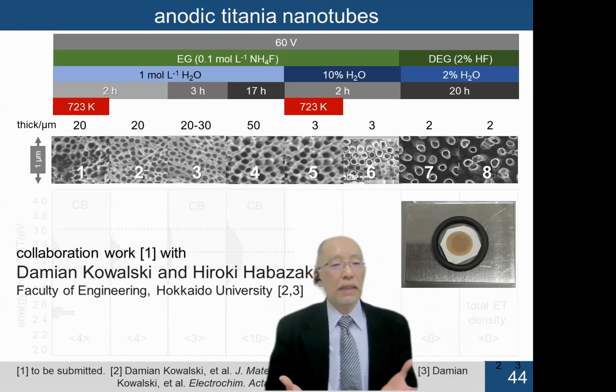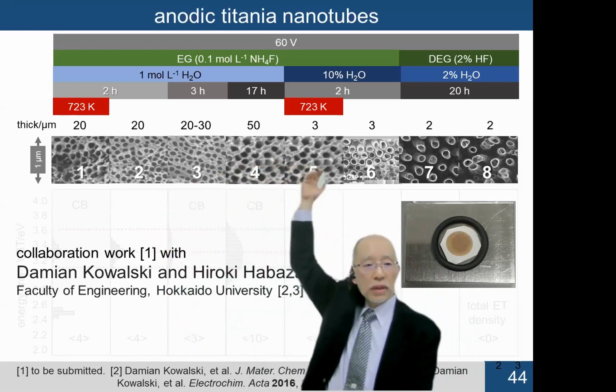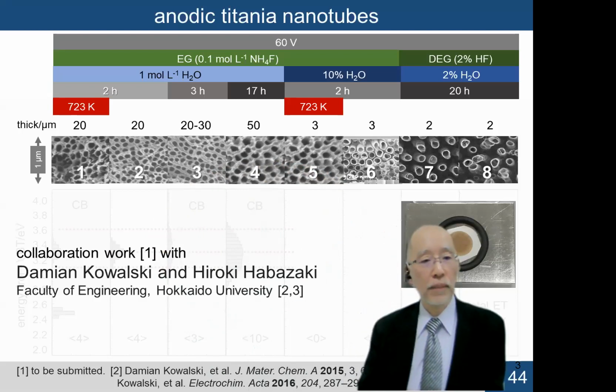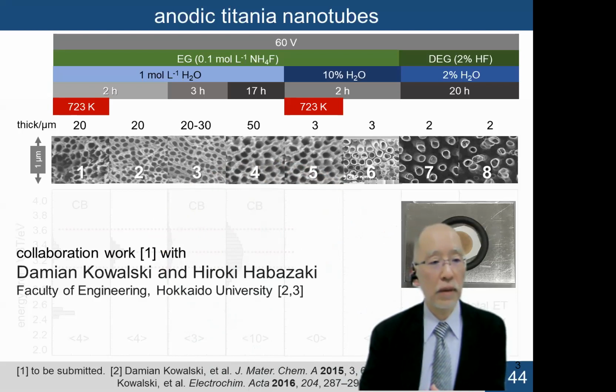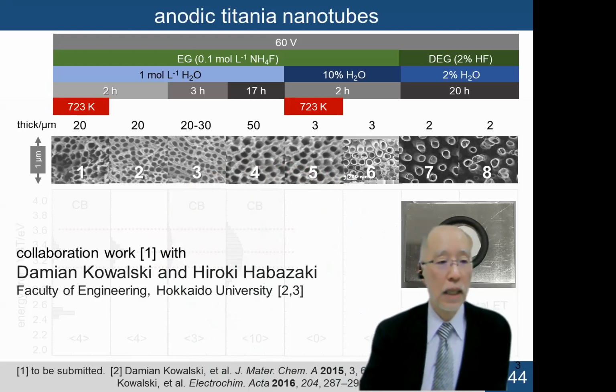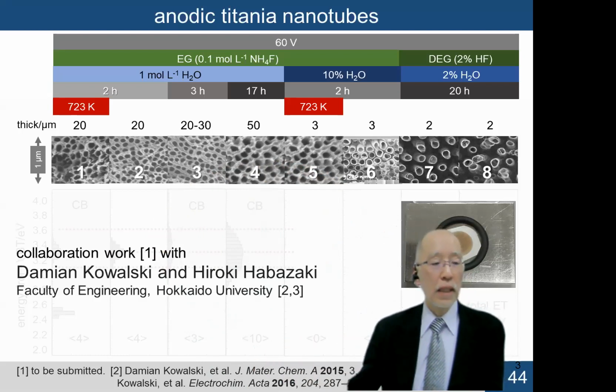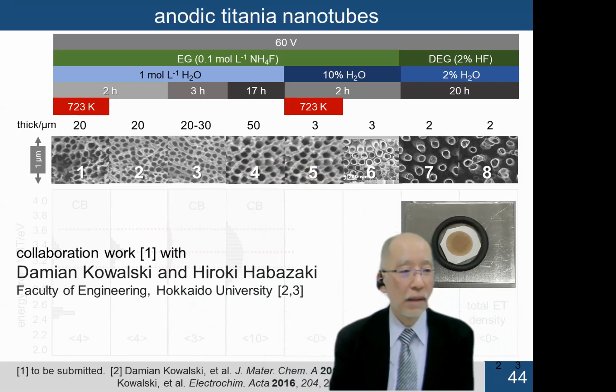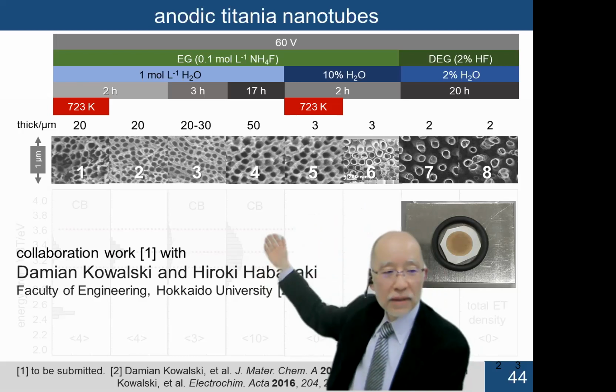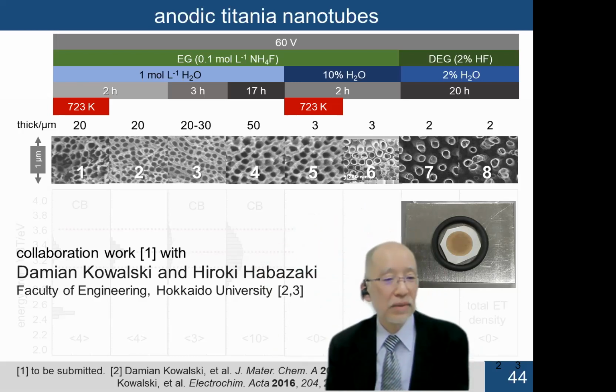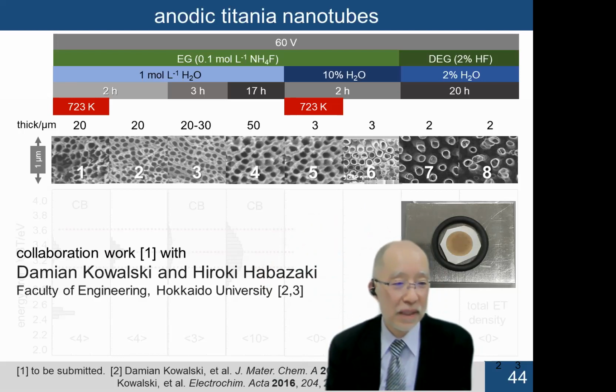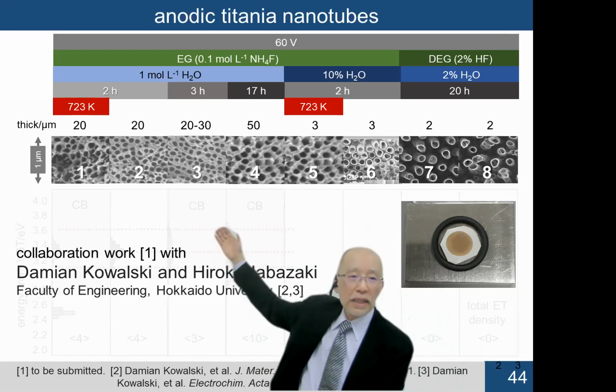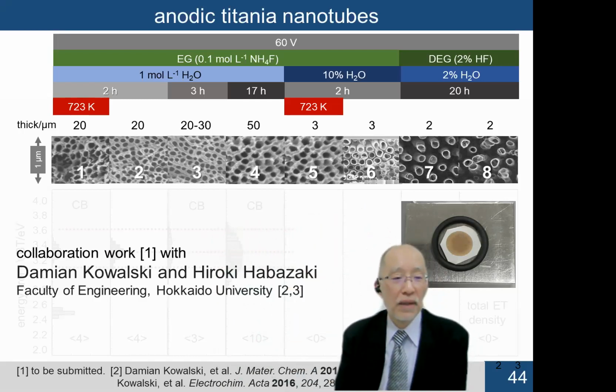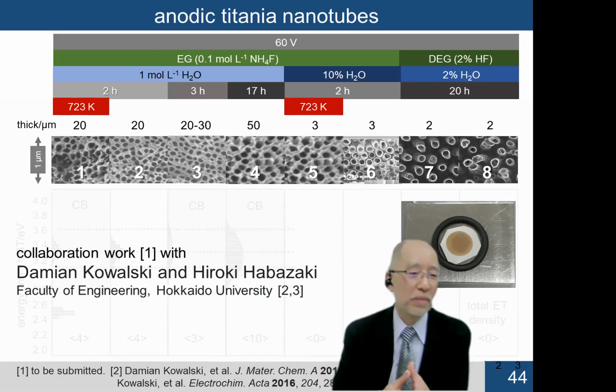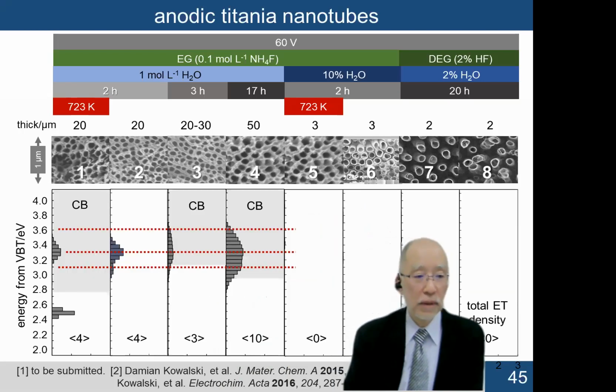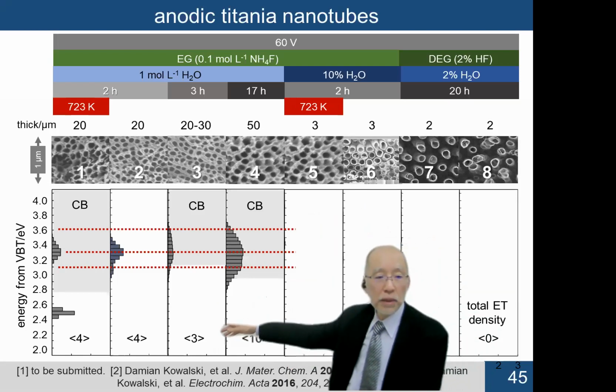And when they are prepared under different conditions, shown here, even with the same voltage, but using a different solvent, different addition of water, different anodization time and heating afterwards, you can see the difference. But the images look the same and don't give any information on how they differ. Even if the performance of those titanium nanotubes is completely different, there is almost no difference, just a nanotube. But our newly developed technique tells those differences in the ERDT pattern.